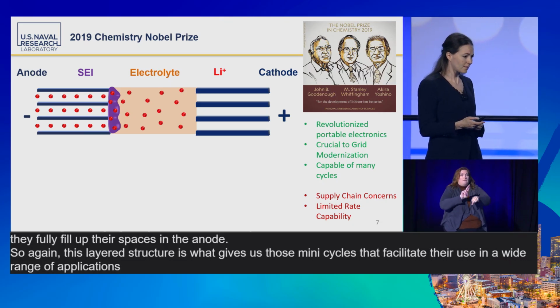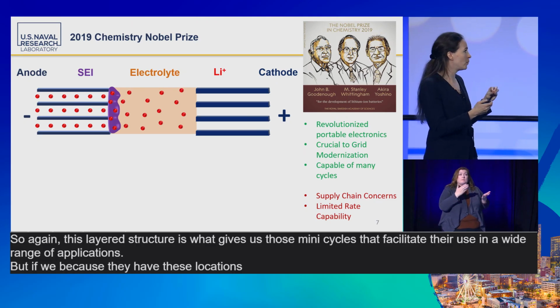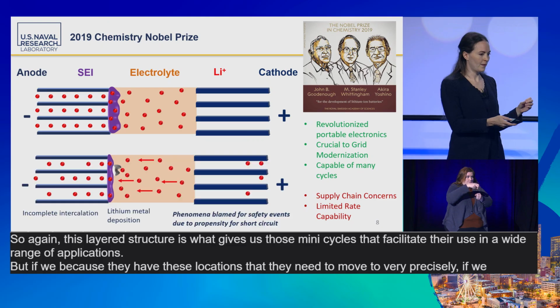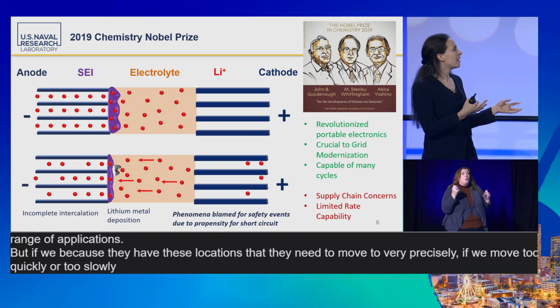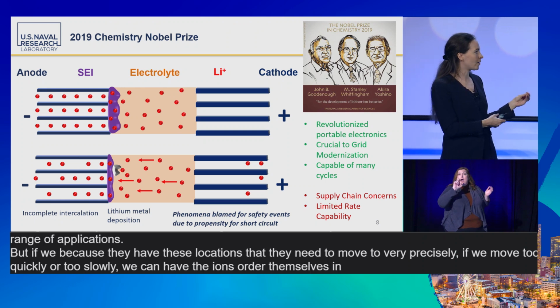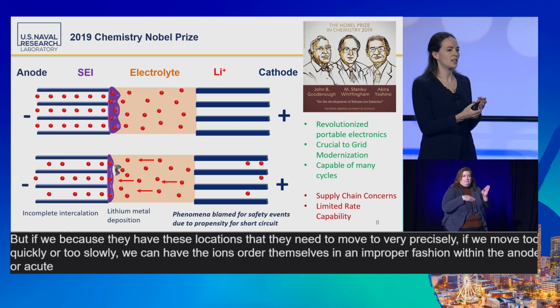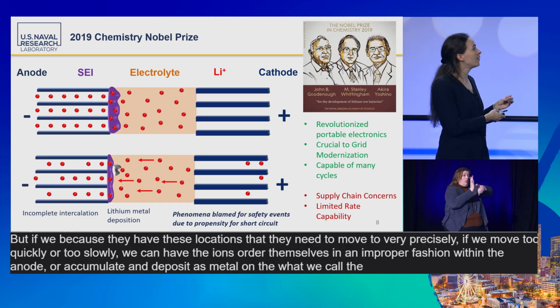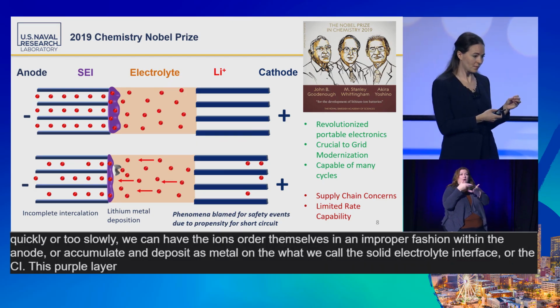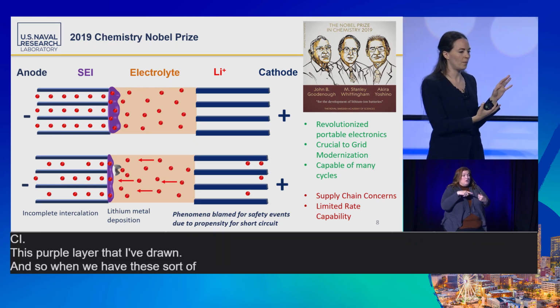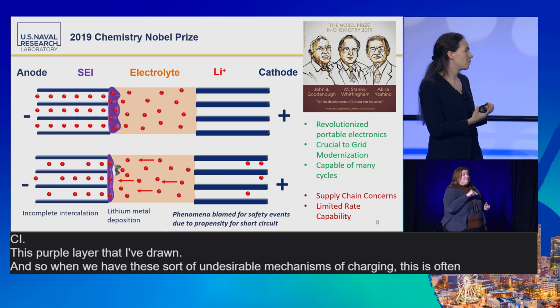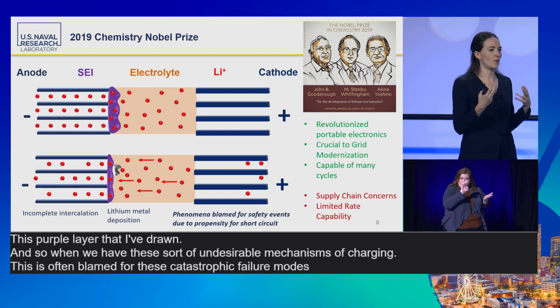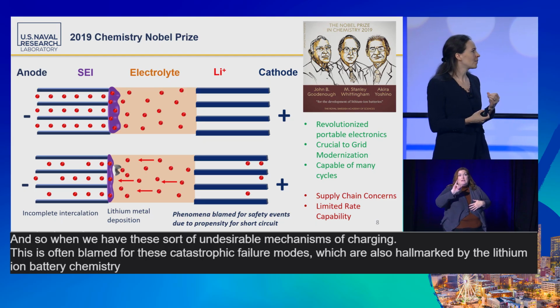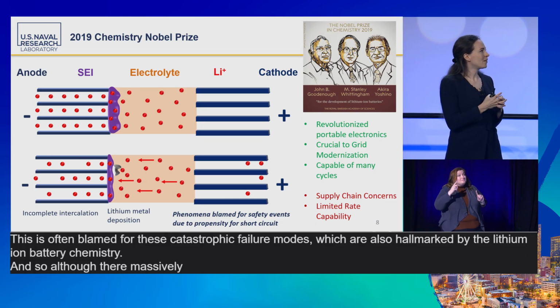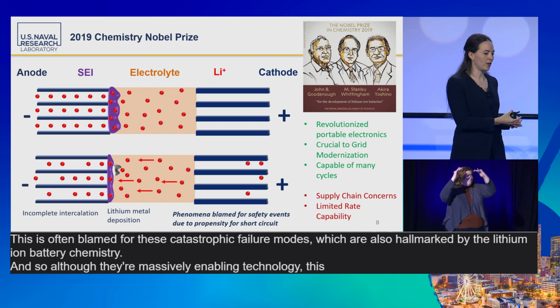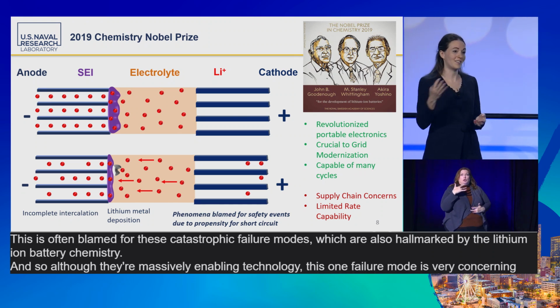But because they have these locations that they need to move to very precisely, if we move too quickly or too slowly, we can have the ions order themselves in an improper fashion within the anode, or accumulate and deposit as metal on what we call the solid electrolyte interface, or the SEI, this purple layer that I've drawn. And so when we have these sort of undesirable mechanisms of charging, this is often blamed for these catastrophic failure modes, which are also hallmarked by the lithium-ion battery chemistry. And so although they're a massively enabling technology, this one failure mode is very concerning and gains a lot of attention.